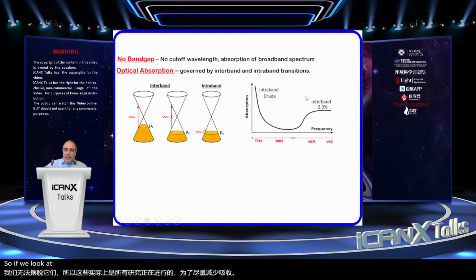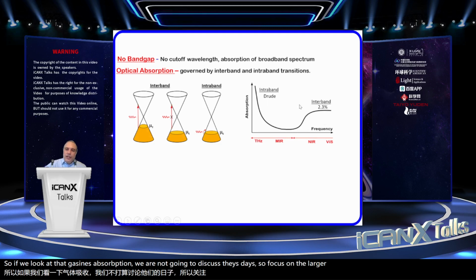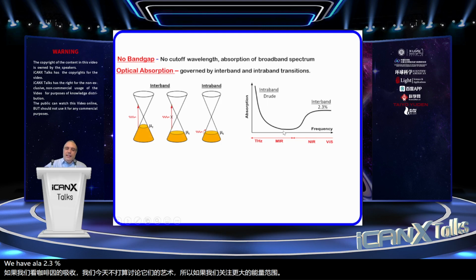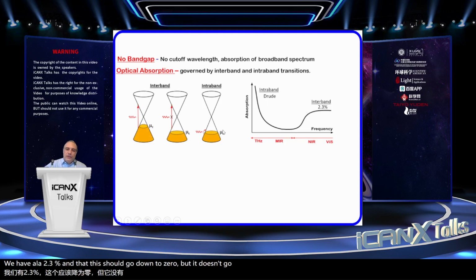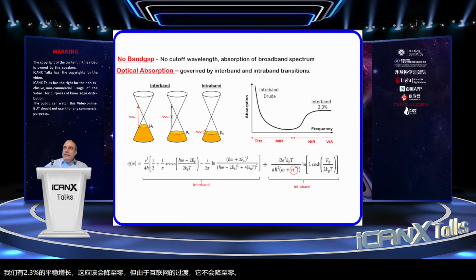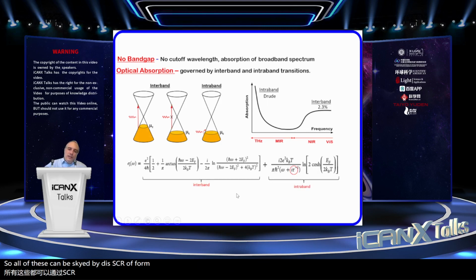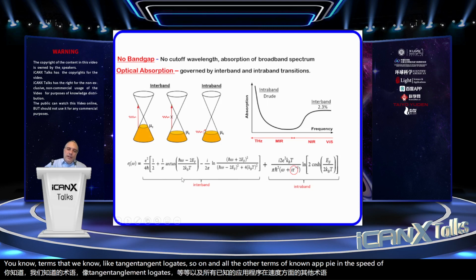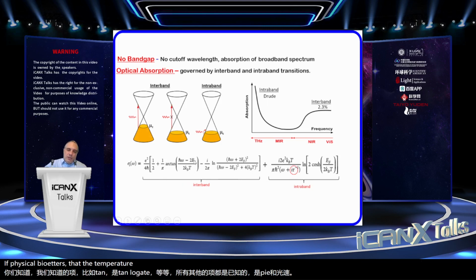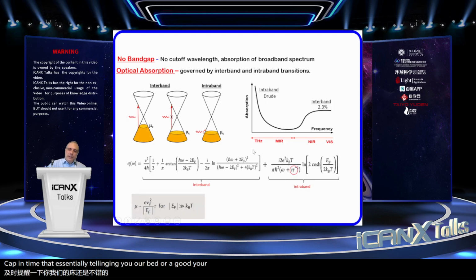So if we look at the graphene absorption, we are not going to discuss terahertz today. If we focus on the larger energy range, we have a flat 2.3%, and this should go down to 0, but it doesn't go to 0 because of intraband transitions. All of this can be described by this Kubo formula that looks complicated, but is actually super simple because it's only terms that we know, like tangent, arctangent, logarithm, and so on. And all the other terms are known, are pi's and the speed of light. The key physical parameters are the temperature, the Fermi level, so the doping, and in particular this tau, this scattering time, that essentially is telling you how bad or how good your sample is.